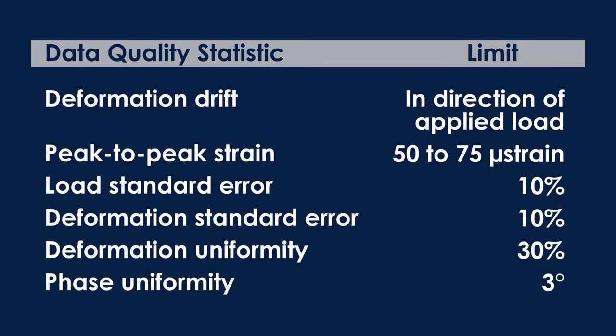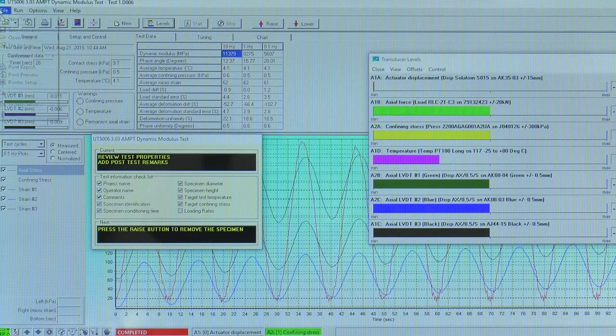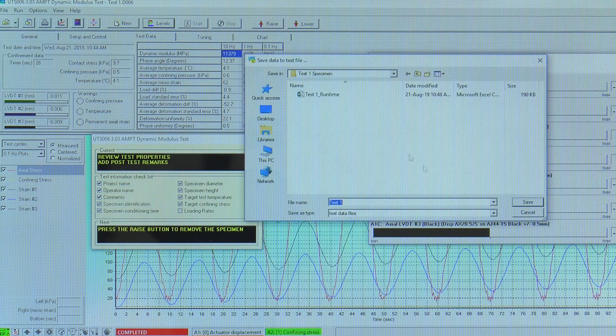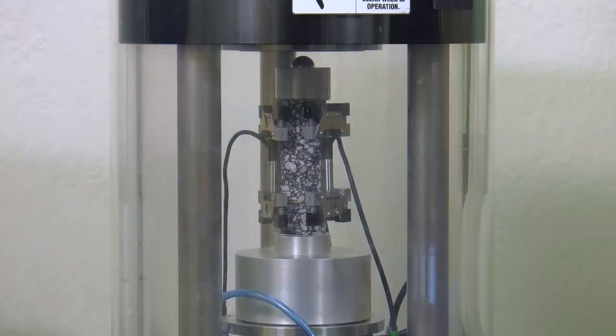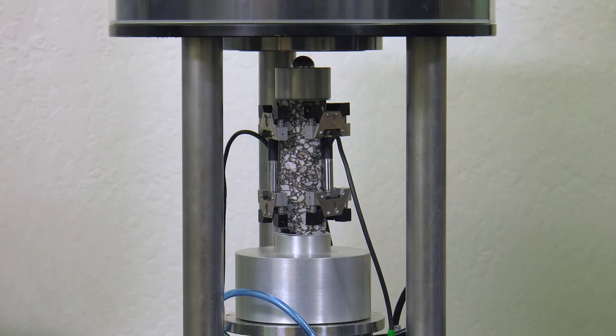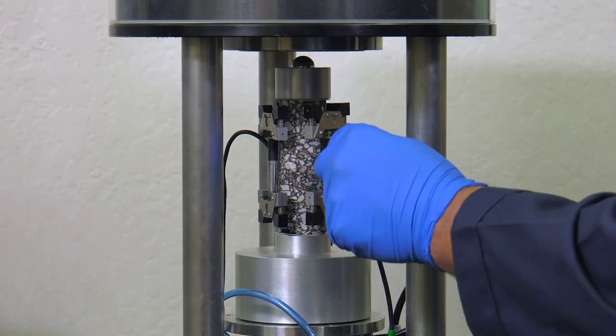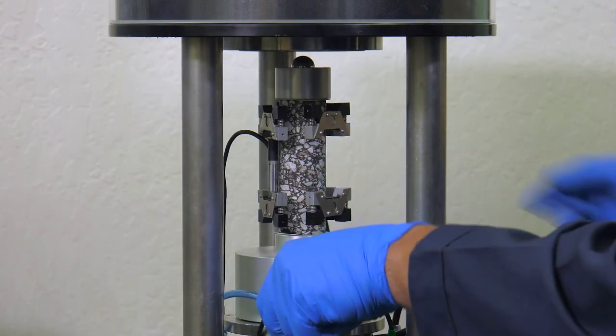Accept only test data meeting the data quality statistics requirements. If excessive amount of permanent deformation has accumulated, discard the specimen and use a new specimen. When the test is complete, export the data. Once acceptable data has been collected, open the AMPT conditioning chamber and remove the tested specimen. Repeat this process for the remaining test specimens.